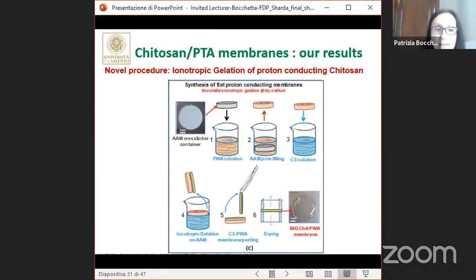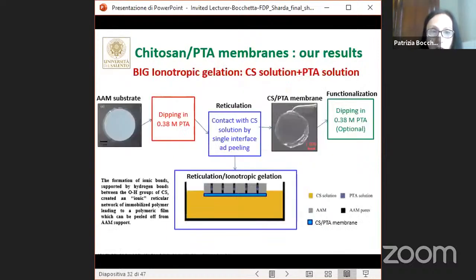After the big process, the membranes were also chemically treated by immersion in phosphotungstate solution for different times in order to study the cross-linking rate of chitosan. The ionotropic gelation through the big method offers the advantage of easily having chitosan synthesis and proton conductive site generation in one single step, because, as said before, the chitosan cross-linker is also the proton conductivity donor to chitosan.